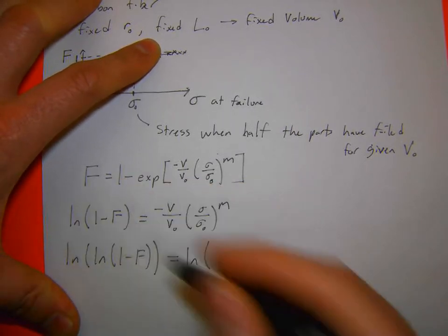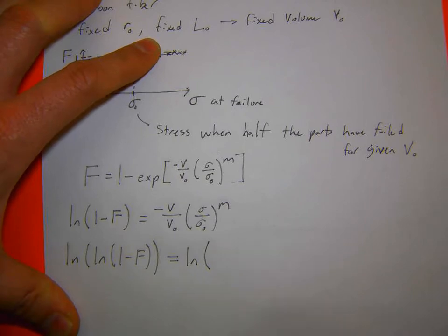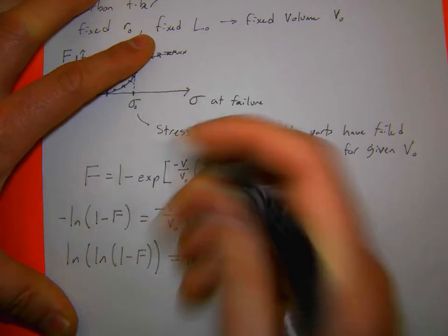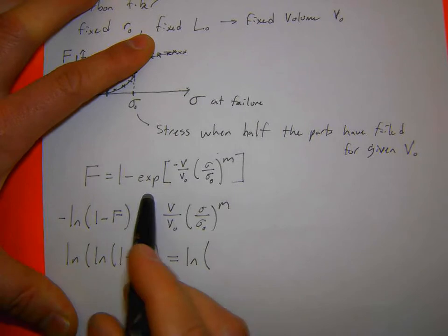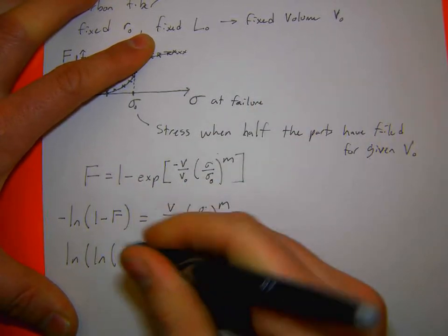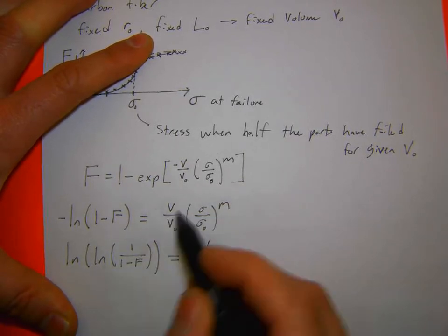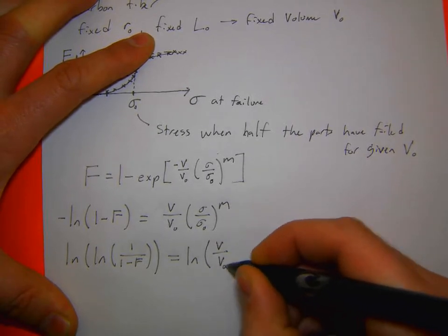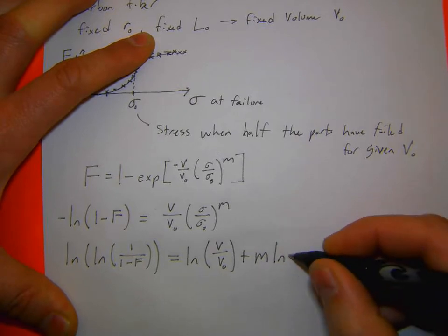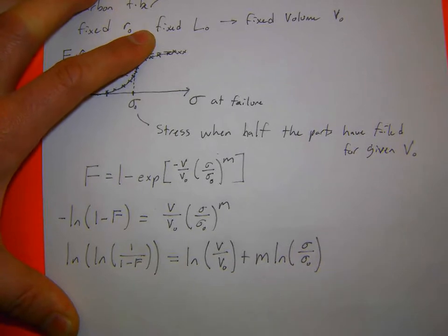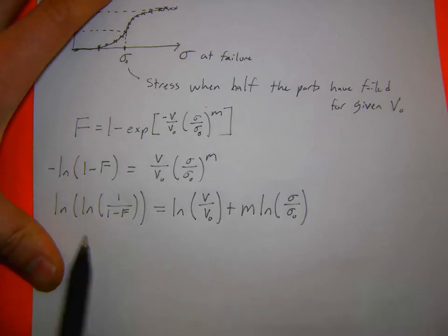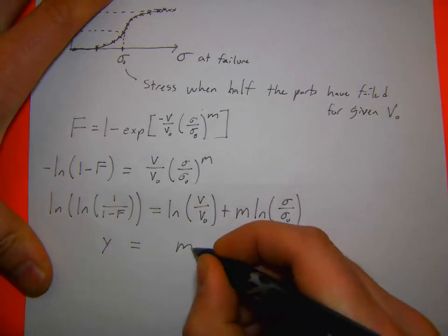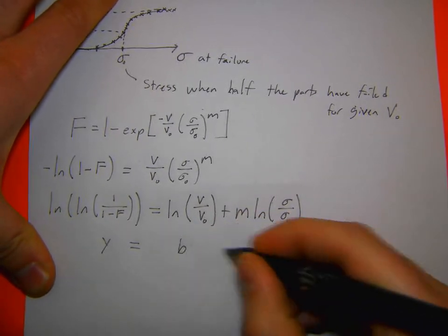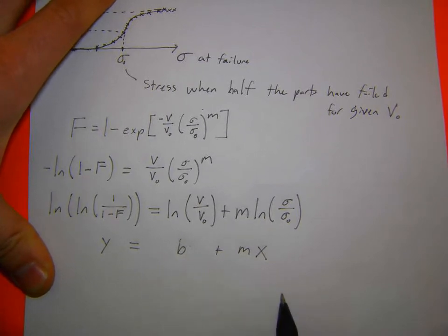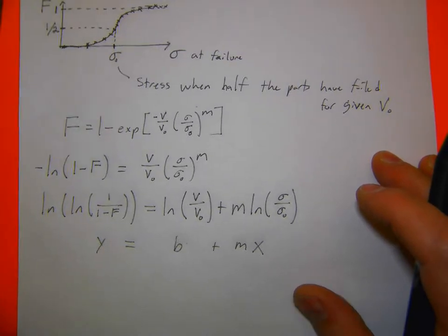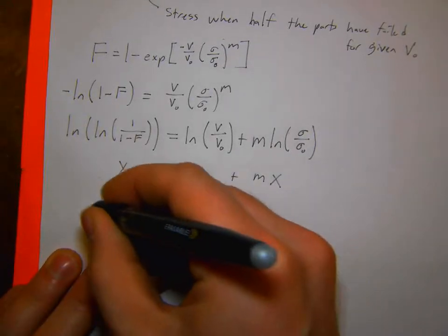If I move this negative over, and if I have negative, I can bring that negative in and flip the sign of this. So this is 1 minus F to the negative 1, which is the same as 1 over 1 minus F. There we go. That's how I get rid of the negative there. This is now natural log of V over V naught plus M natural log of sigma over sigma naught. So this is slightly convoluted, but the reason we do this is now we have some Y equals B plus MX. So now I have a linear equation, which is a lot easier to look at and analyze. So I'm going to take that Y equals MX plus B form, plot this out,